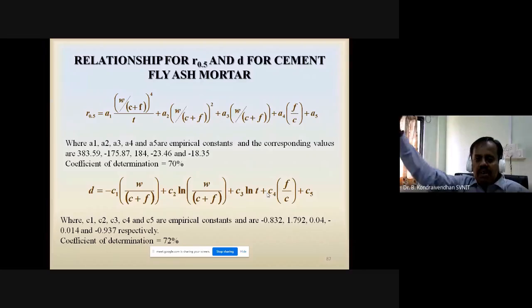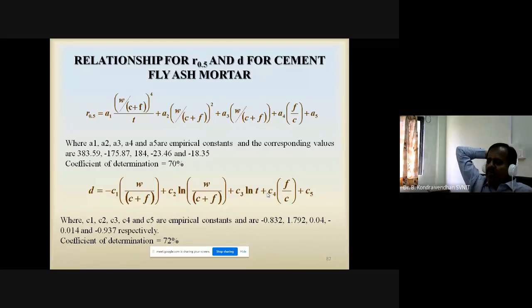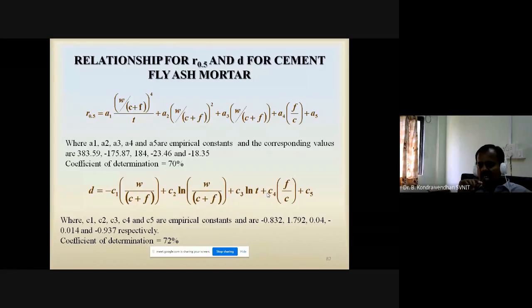Then we have gone for the cement fly ash mortar. Here also the problem is there, because once we introduce the sand, no ITZ porosity quantification is available in the literature. Again, doing this is a very voluminous work, because we have to change the paste content and use different volume proportions of the aggregate. We have to do separate research on that, then only it is possible. Initially we have taken only one paste content. We have to take more paste content as compared to the void ratio. That kind of exercise we have not done. That's why it is not possible to do the modeling in the case of the cement fly ash mortar also.